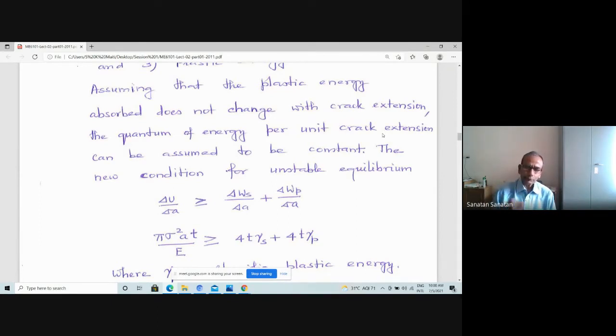So that energy should also be supplied. So they assume that the plastic deformation energy is constant per unit crack extension, and therefore if that is the case, then we can actually write the energy balance, the equation slightly modified. Left is strain energy per unit crack extension, right is surface energy per unit crack extension, plus plastic energy per unit crack extension. So if we assume that plastic energy per unit crack extension is gamma P, and T is the thickness of the plate.